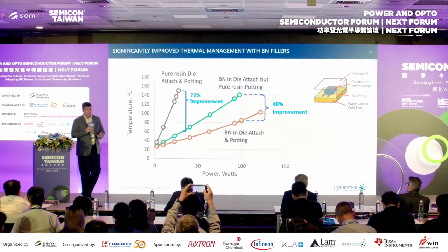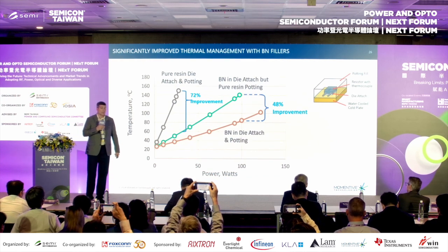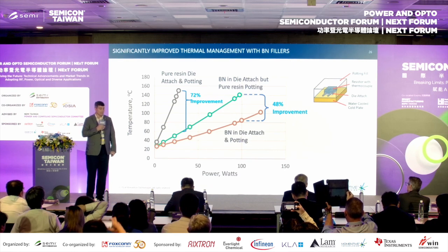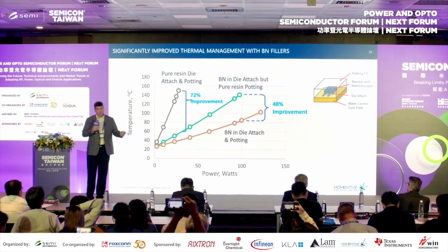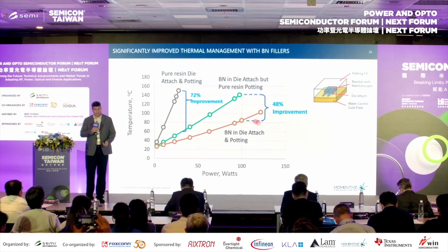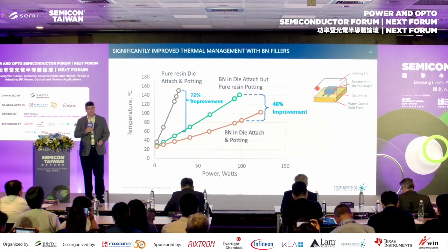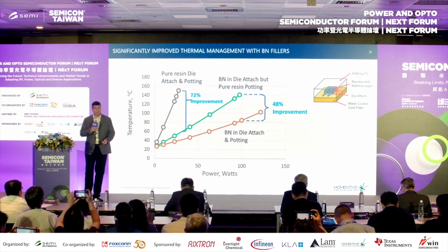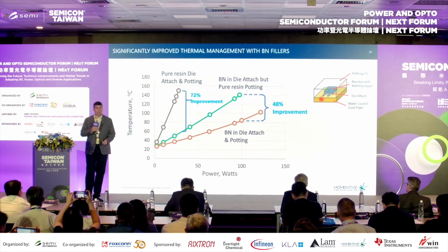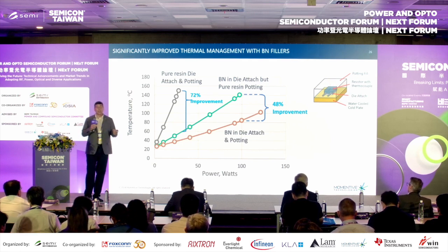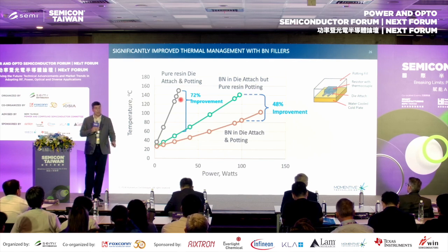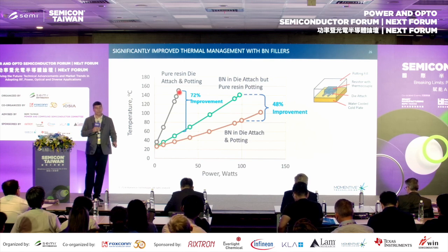But again, the key component here was how does it actually affect the thermal performance of the system. So here we did a simple example, right? Nothing too complicated. This is a simple resistor acting as a heat source with both a die attach going down to a water-cooled plate and then a potting around the whole system. So first we did it with neat resin, right? That's shown here. Even at about 30 watts, you got temperatures of about 150 degrees Celsius.